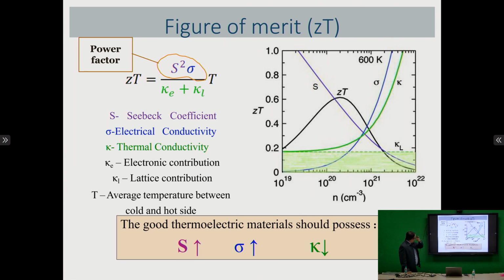Then, as you can see, the ZT parameter I told you about, it has recently been found that if you achieve ZT greater than 2, the efficiency of any instrument working with this will improve. Thermoelectric generator efficiency will be improved by about 30% more. Recently, at room temperature, bismuth telluride is used as a good thermoelectric material, and its ZT is about 1. So our aim is to get a high ZT, this figure of merit, for these materials.